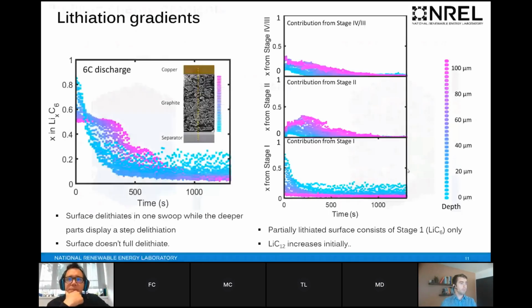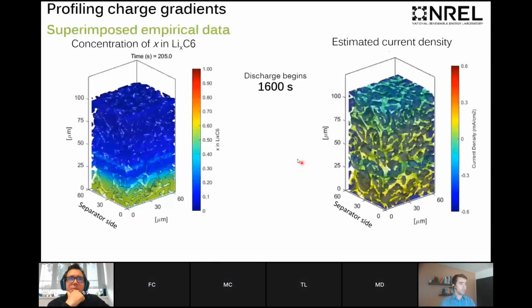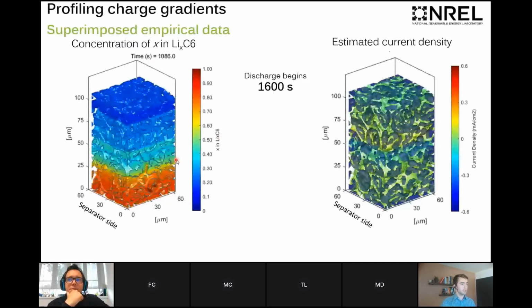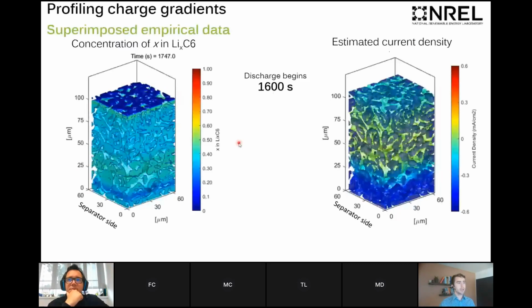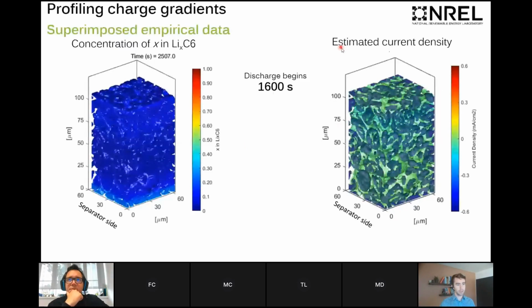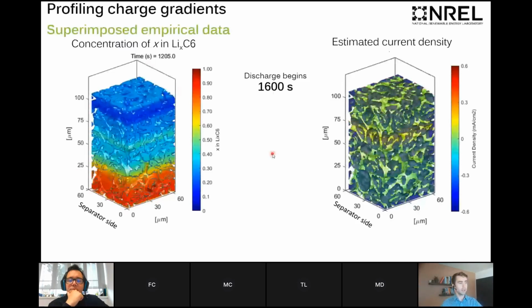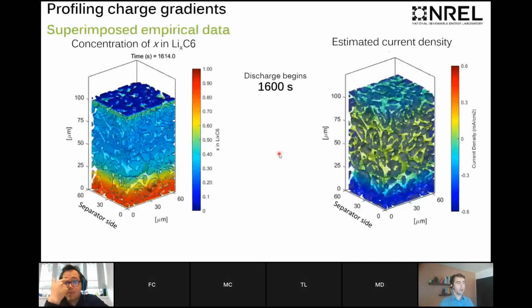So in summary, the major limitations associated with fast charging are caused by lithiation gradients. This is the data superimposed onto a nano-CT image of graphite. And we also see that there are very severe current density gradients as well at certain periods of time during fast charge and discharge. You can see a short-lived red region there. And lithiation gradients are the biggest problem to resolve for fast charging issues in thick electrodes.